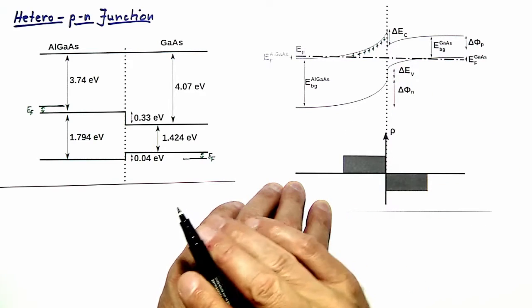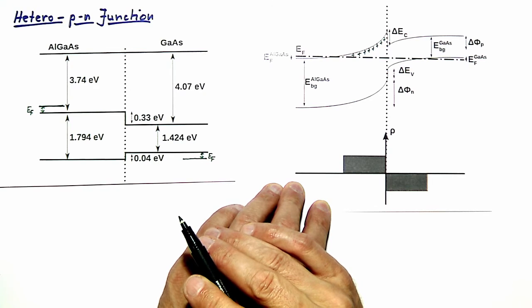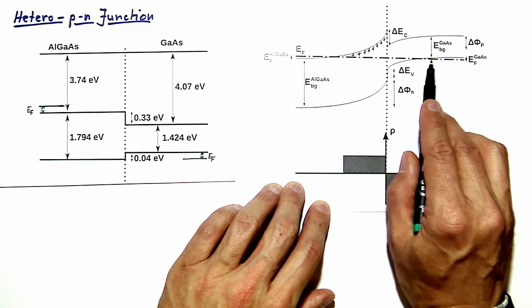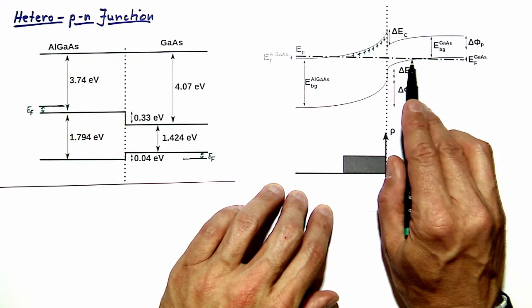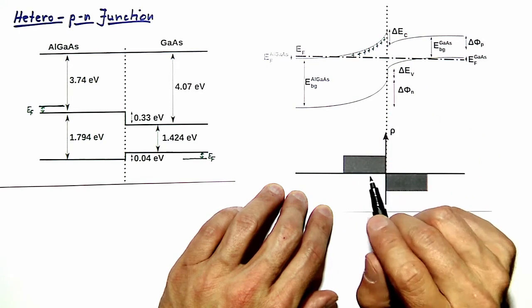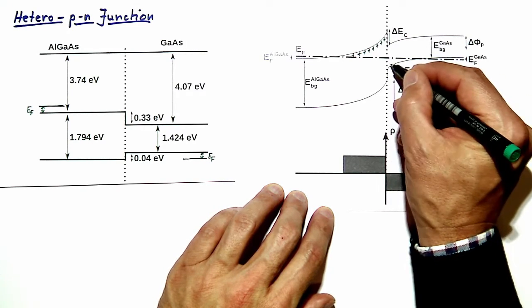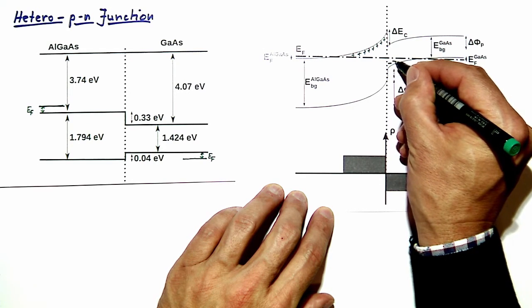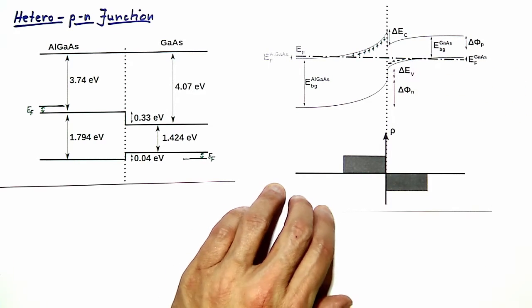These electrons go into the gallium arsenide and must occupy available acceptor states that lead to the p-doping. In the bulk region, the system is locally charge neutral. But if the Fermi energy moves above the valence band edge, the acceptor states become locally charged — since their energies sit close to the band edge — giving rise to a negative space charge region.